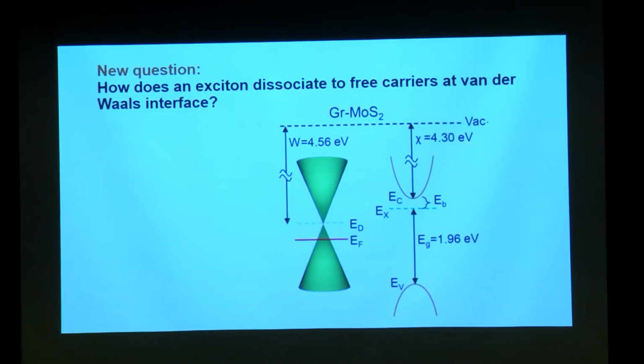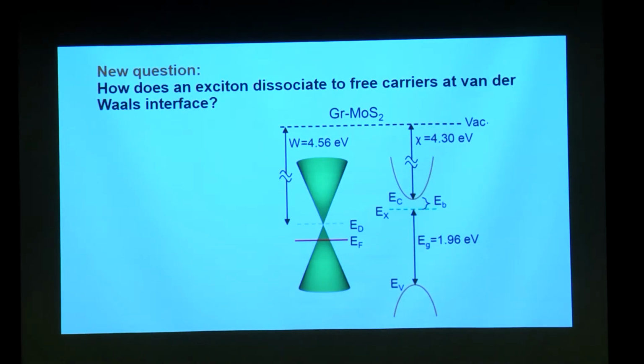So, the light to electricity conversion: how does an exciton dissociate into free carriers at a van der Waals interface? Let's look at the basic band diagram. This is the graphene, and this is the molybdenum disulfide. This is where the conduction band is, and this is where the excitonic state is, which is an energy EB below the conduction band minimum.